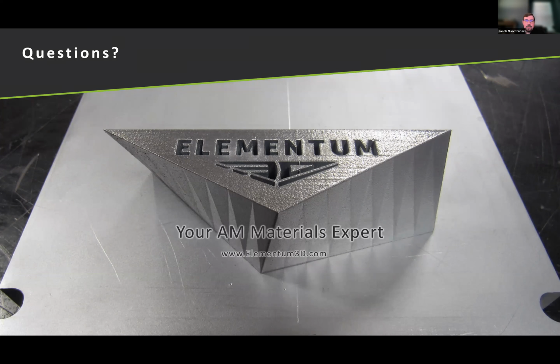The percent IACS, we have this listed on our website. Like I say, you can get to higher conductivities if you do double passes, but we see about 80 to 85% IACS when done properly with thin walls and other scenarios and overhangs. It depends on the shape of the part and how you're measuring that conductivity. We found it can be wildly variable, with everything as low as 70%, depending on the application. So we list 70% IACS on our data sheet to cover that.